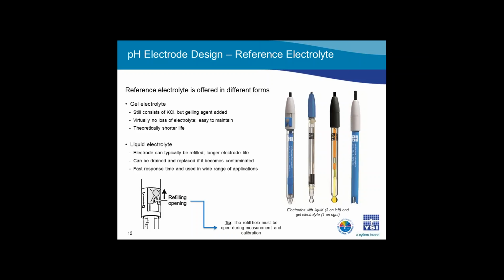All YSI refillable lab electrodes use 3 molar KCl for the reference electrolyte, but other manufacturers may use slightly different forms. One important tip I did want to mention is that if your electrode is refillable, it is very, very important to have the refilling opening in the open position during calibration and measurement, as you can see here.